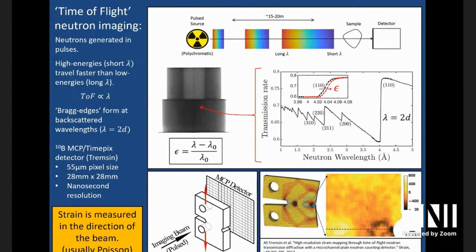Yeah, and that was my point that I was getting back to this picture for. The other issue is that we make a measurement on an edge. We pick an edge for reasons like, for example, it's a big edge, or it's sharp, or it's referring to isotropic properties or whatever. So we're really only looking at that tiny set of wavelengths around that, and we threw all those other neutrons away, right? So obviously, there are other ways of speeding this up by looking at the whole pattern as well, because there's information everywhere on that line.